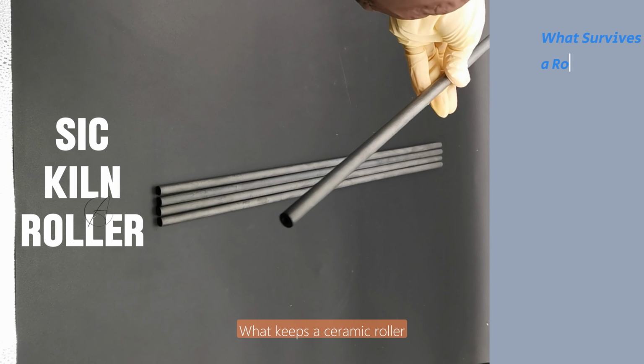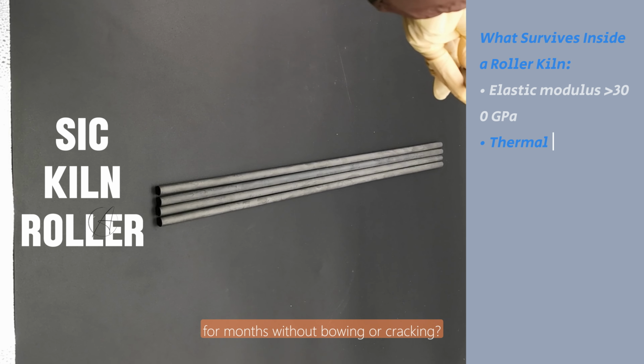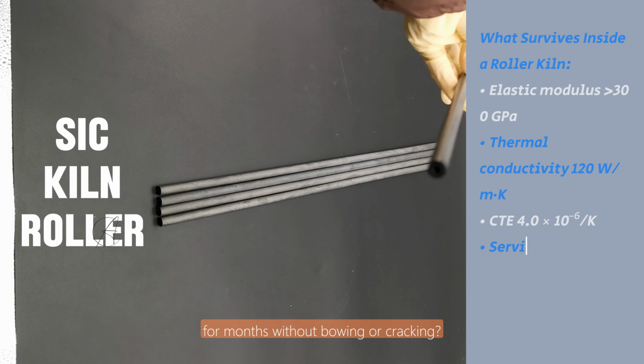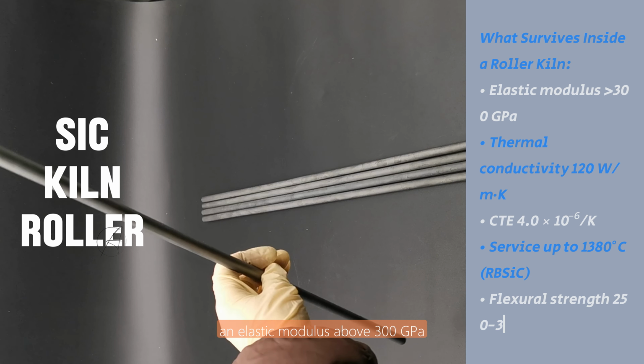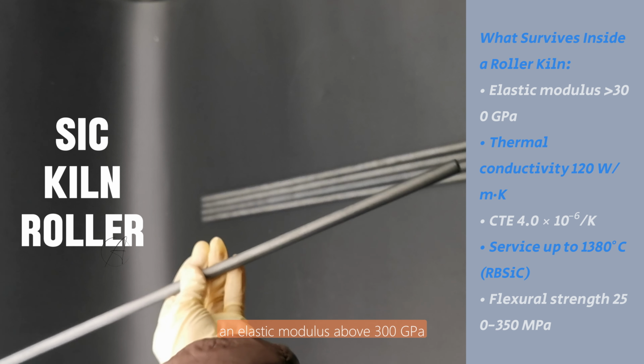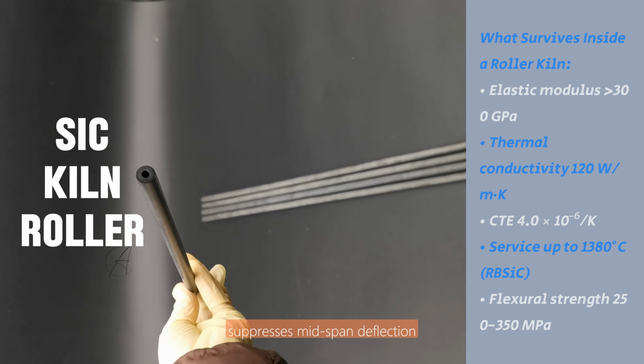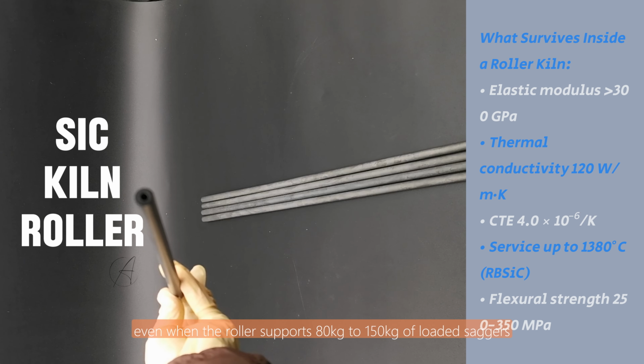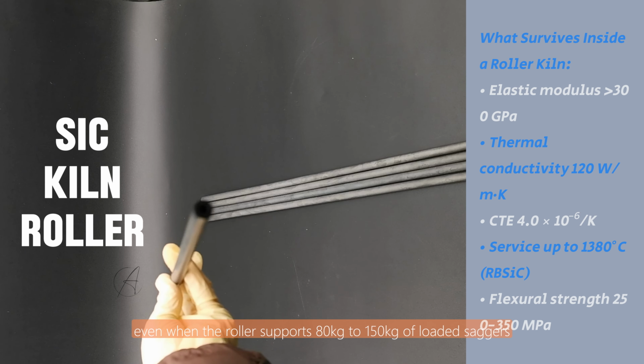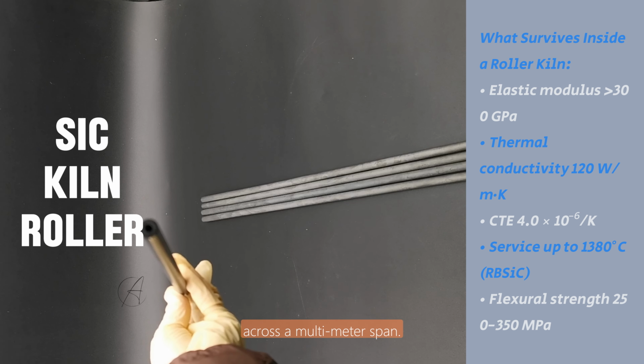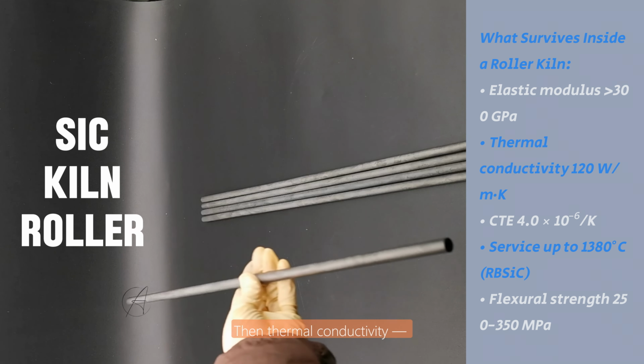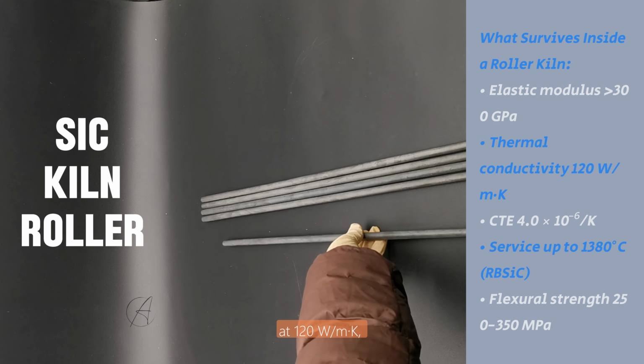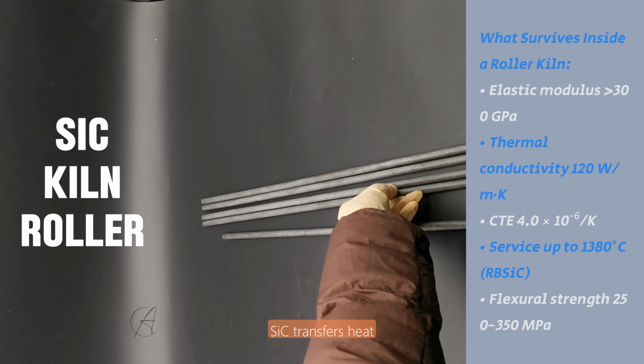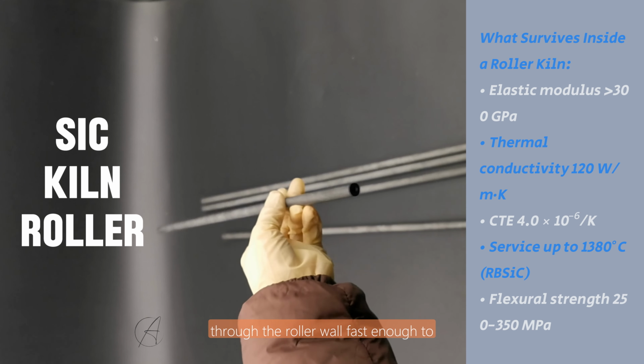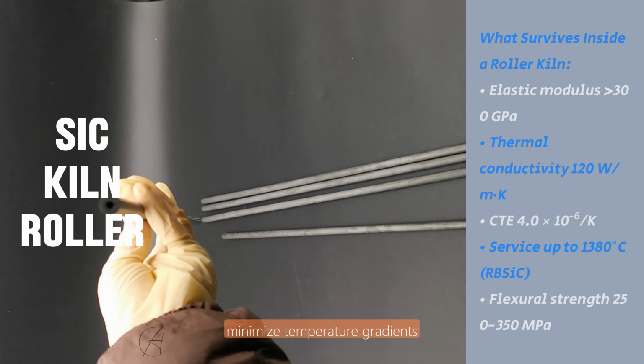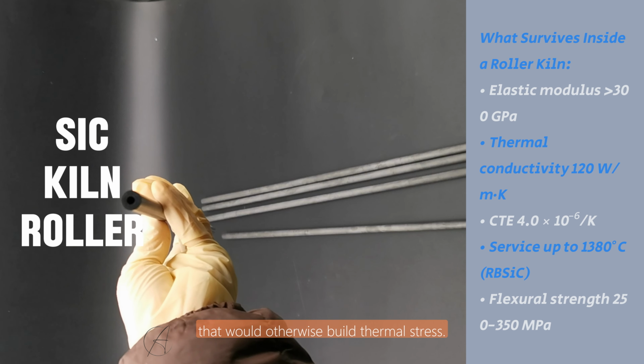What keeps a ceramic roller running under load inside a furnace for months without bowing or cracking? Start with stiffness. An elastic modulus above 300 gigapascals suppresses mid-span deflection, even when the roller supports 80 to 150 kilograms of loaded saggers across a multi-meter span. Then thermal conductivity. At 120 watts per meter Kelvin, silicon carbide transfers heat through the roller wall fast enough to minimize temperature gradients that would otherwise build thermal stress.